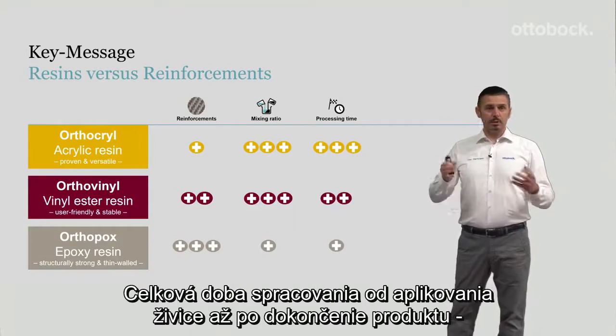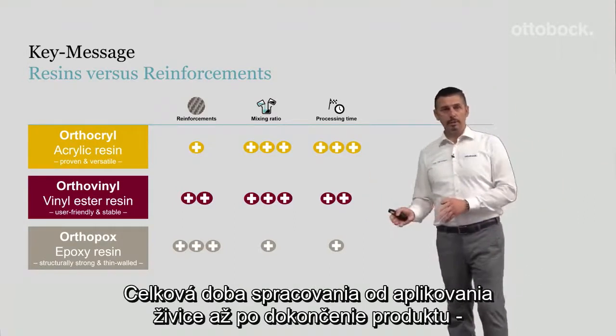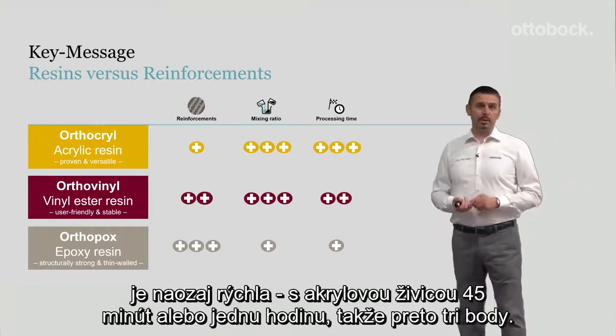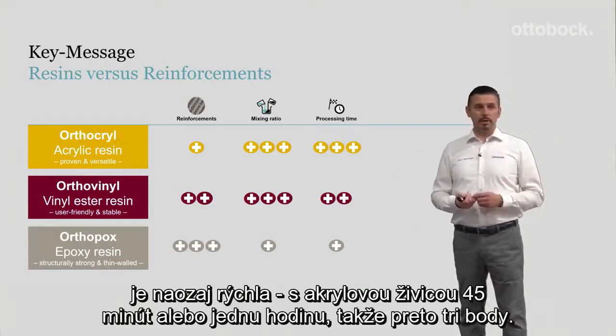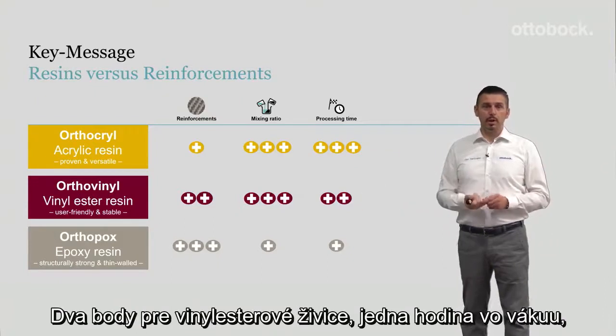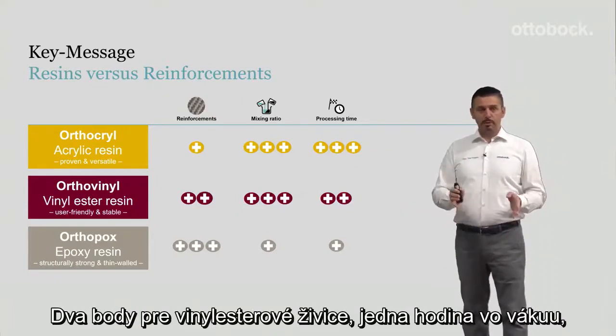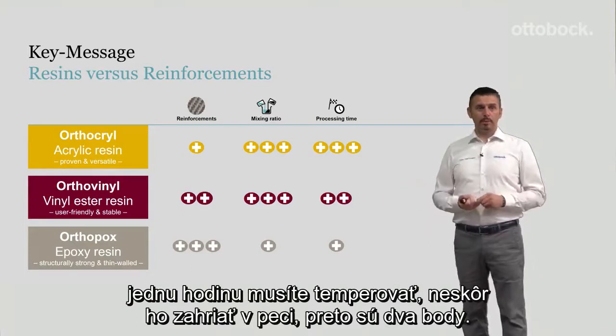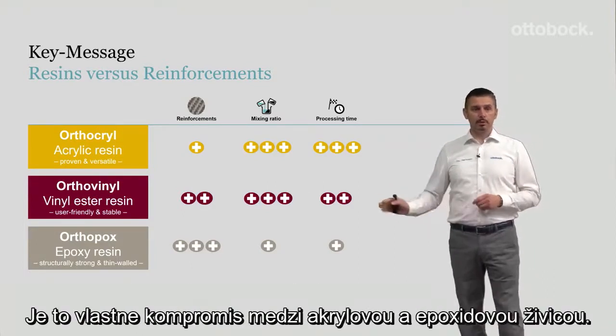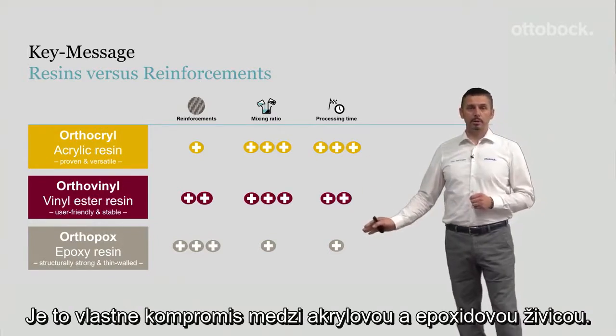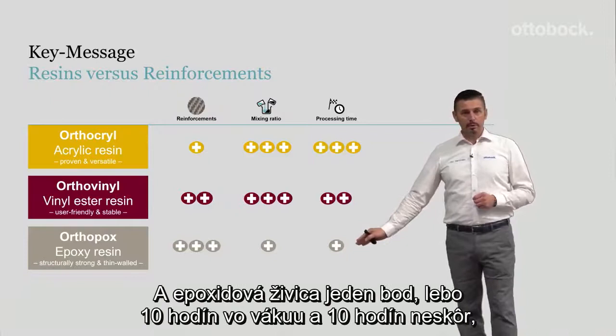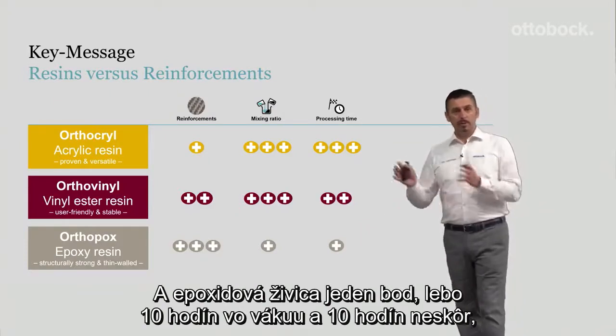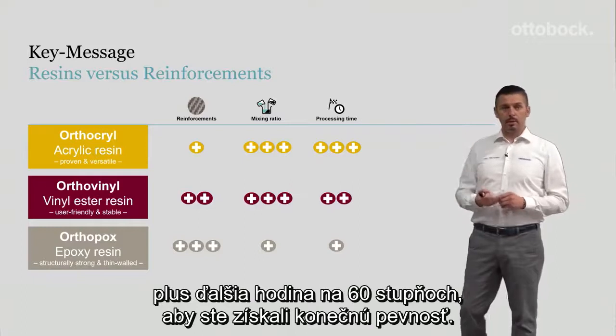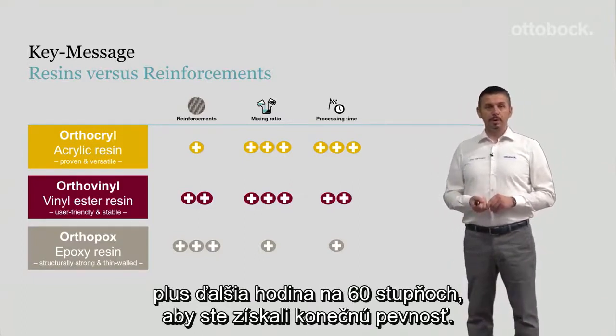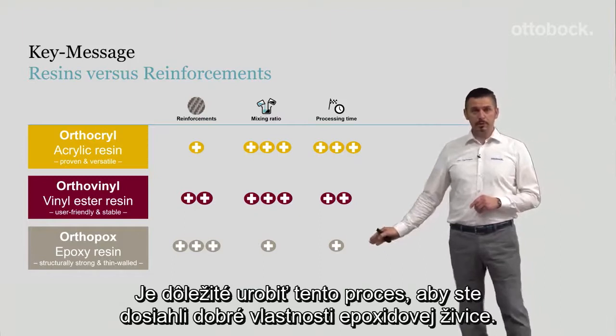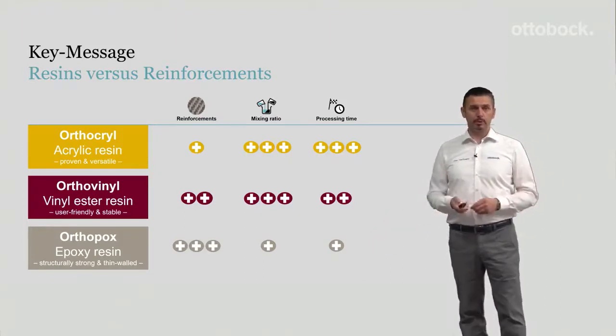The processing time in total, from stirring the resin until the product is finished. With acrylic resins it's really quick, 45 minutes to 1 hour, so that's why 3 dots. 2 dots for the vinyl ester resins: 1 hour in the vacuum, 1 hour you have to temper, anneal it in the oven later, so it's a compromise between the acrylic and the epoxy resin. And the epoxy resin, 1 dot, because 10 hours in the vacuum and 10 hours later, plus another 1 hour at 60 degrees to get the final strength. It is important to do this process to get the good properties of the epoxy resin.